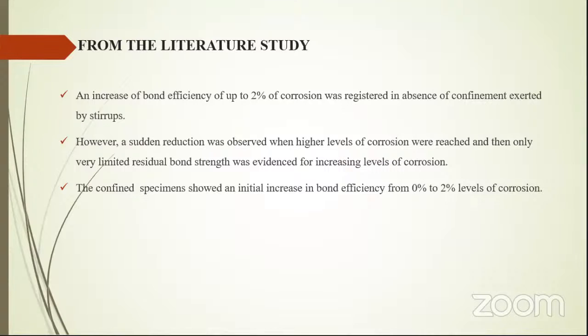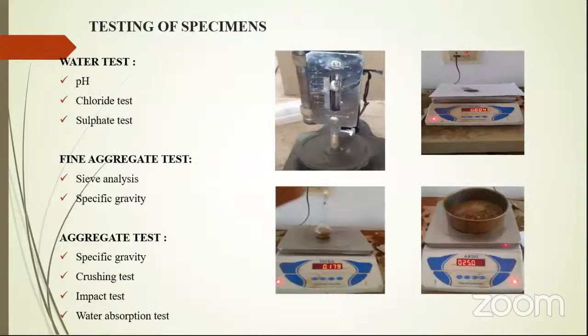From the above literature study, we can take some points: an increase of bond efficiency of up to 2% of corrosion was registered in absence of confinement exerted by stirrups. However, a sudden reduction was observed when higher levels of corrosion were reached, and then only very limited residual bond strength was evident for increasing levels of corrosion. The confined specimen showed an initial increase in bond efficiency from 0% to 2% levels of corrosion.